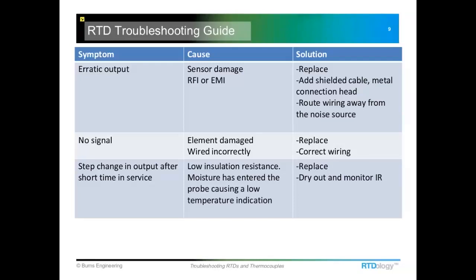And I had one, I'd mentioned insulation resistance or moisture getting inside the probe. This is another common failure mode. And what this will look like is over time, you may see that the temperature measurement started out and it's been correct and everything's working right. And then it'll slowly creep down. For no particular reason, you think your system is still running correctly, but that temperature has just kind of dropped a little bit. And this will be an indication that moisture has gotten inside the probe.